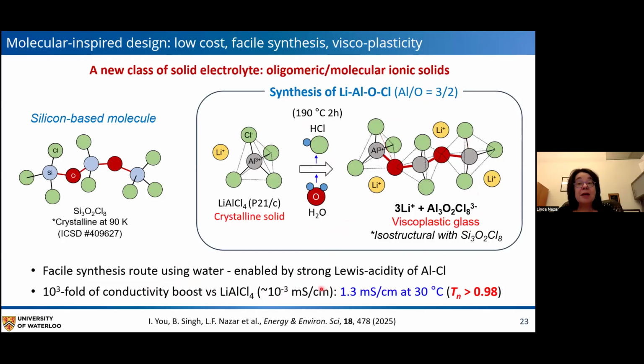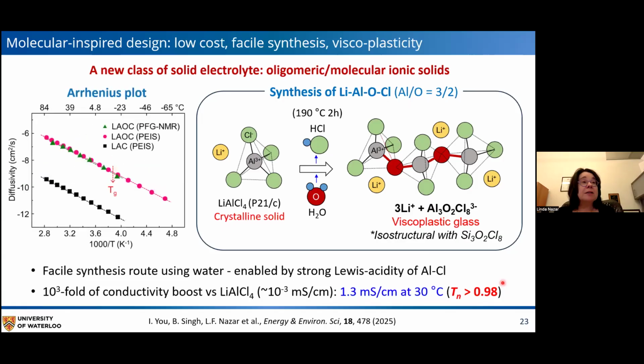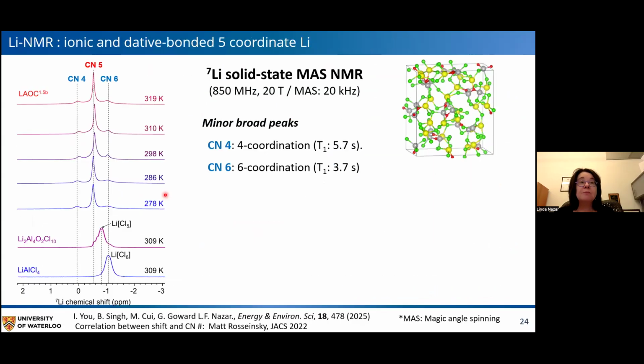But anyway, we have a conductivity that's around 1.3 millisiemens and a transference number that is in excess of 0.98, whereas some of the other materials had transference numbers much lower, on the order of 0.69. So that's why we think that this is a different material. And this just shows diffusivity data collected both from EIS and PFG NMR, showing the PFG and EIS data are right on top of one another.